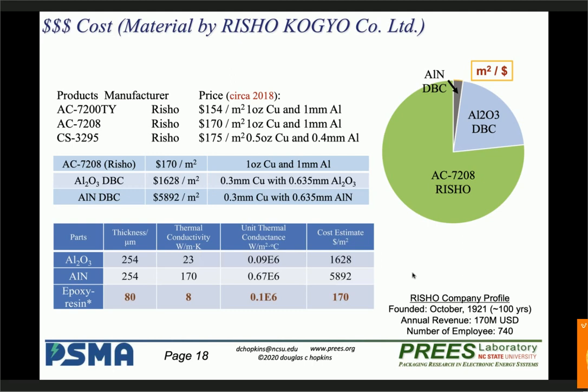This is the cost performance. You can see that aluminum nitride, this is how much space you get per dollar. So instead of dollars per meter squared, we did meter squared per dollar. But if you want to look at what the cost of the materials are, you can see that they're substantially lower in cost. Right here on the right-hand side, this is the dollars per meter squared, and alumina is pretty cheap. Aluminum nitride ups the cost substantially, and the epoxy resins for substrates is very low. Again, it'll be a much lower profile, lower cost as far as material goes. Again, you're dealing with larger sheets, so you have lower manufacturing costs. So it's a lower cost, better performance, but you can't compete with aluminum nitride.